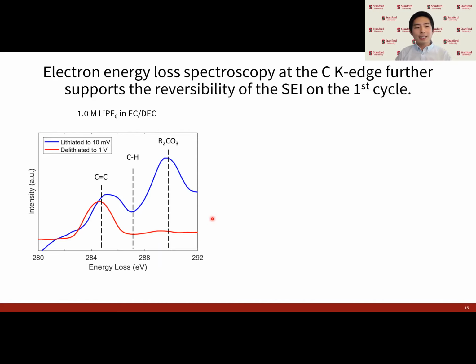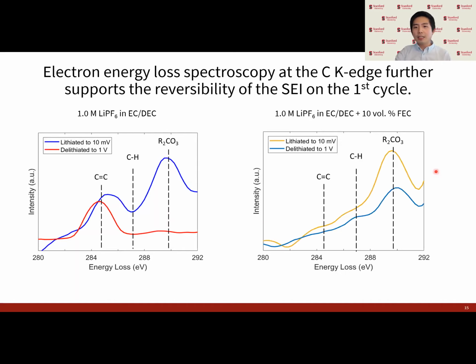So in this kind of STEM EELS mapping, we also have access to the raw spectra. And EELS is a very powerful technique because we're also sensitive to the bonding states. Looking at the carbon K edge, we can see there are strong carbonate peaks in the SEI on lithiation, that then oxidize away on delithiation. With the addition of the FEC, these carbonate peaks remain robust on both lithiation and delithiation, suggesting that the polymerized FEC product is contributing to the stability of the silicon anode.